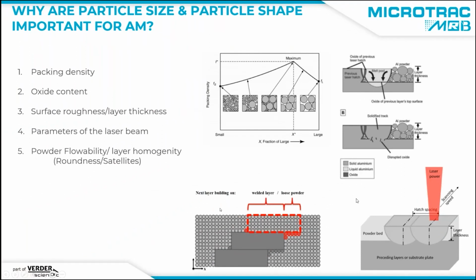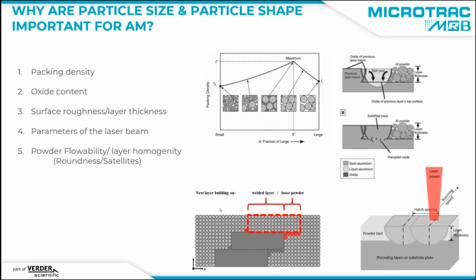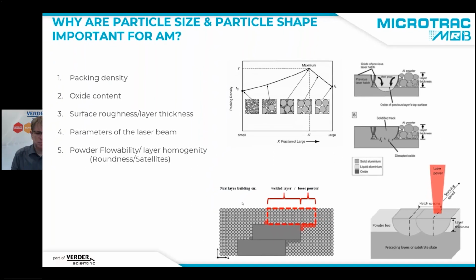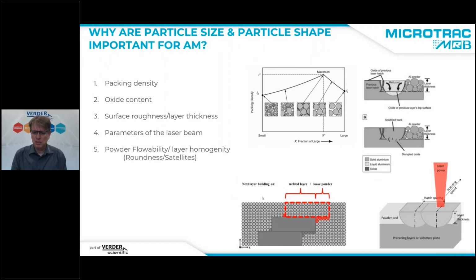Then there are surface roughness and layer thickness. Additive manufacturing is in many cases a layer by layer process, and of course if we have large particles we cannot achieve thin layers. The parameters of the laser beam also depend on the properties of the powder. If we have larger particles, we need a different energy to melt them than with smaller particles. And last but not least, we are creating layers in the manufacturing machine, and the flowability of the powder has a big influence on the homogeneity of the layers. If we have a nicely flowing powder which consists of round particles with a small number of satellites, then we can achieve a more homogeneous layer than with irregularly shaped particles. In general, there are always exceptions to the rule, but this is the basic idea.